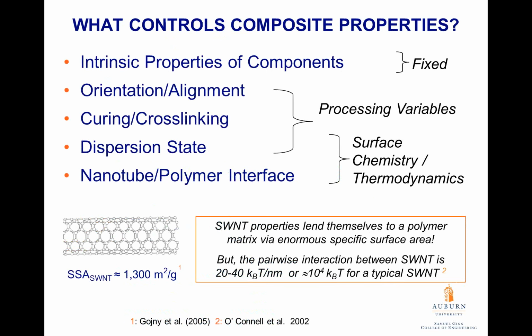So when we make a composite, the properties are controlled by the intrinsic properties of those components. Carbon nanotubes are about 100 times stronger than steel, at 1/6 the weight. That sounds great, but we're not going to build a bridge or make a car out of a single nanotube. We need to get those amazing properties ported to a real system. So we have the intrinsic properties that affect things. Then we have all our processing variables, especially that dispersion state, or if we're thinking about an epoxy system or another thermoset system, curing and cross-linking. And then we have the interface, which is surface chemistry and thermodynamics.